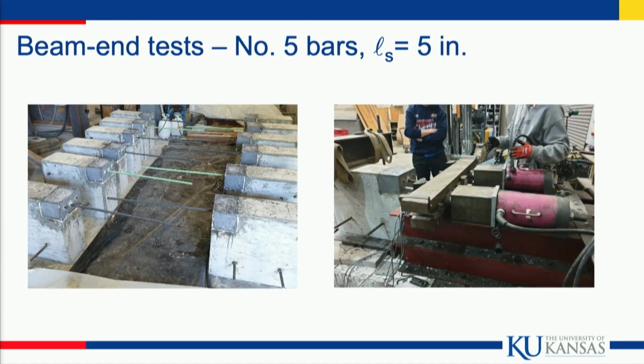So the next step was an ASTM beam-end test. In this case, and I have a pointer here, but these are blocks of concrete. If you look carefully, you will see this kind of concrete looks a little bit different where the bars are sticking right into the test specimen. That's the UHPC. Splice length was 5 inches. These are number 5 or 5/8-inch diameter bars. We pull on the bar, push on the concrete away from the bar, and get different strengths.